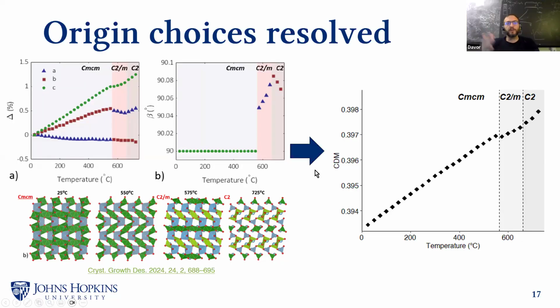Yes, so at this certain temperature, there is a shift in peaks and the appearance of some new peaks after the phase transition, meaning they cannot be explained anymore with the orthorhombic, this Cmcm structure. So you do need to use a monoclinic structure to fit the data after the transition. But it's the same sample continuously heated, and X-ray is taken at every temperature that we stabilized our sample, using powder X-ray diffraction to determine the structure every time. Yes, and then, of course, doing a Rietveld refinement on each of these collected data sets.